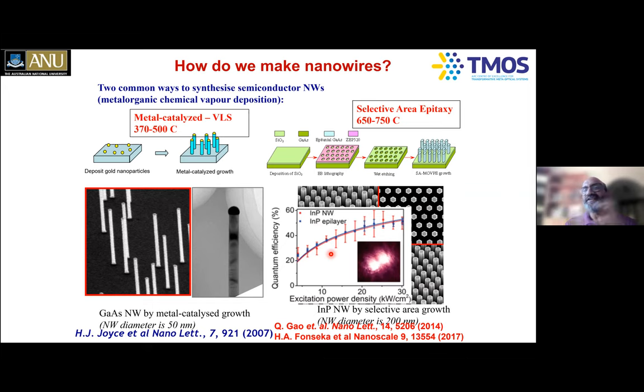And you can make use of these indium phosphide nanowires for making lasers, solar cells or infrared detectors, whatever optoelectronic devices you want to make, which I will come back to. But that is not always the case. In the case of gallium arsenide, the broken bonds on the surface really create defect states within the band gap of the semiconductor. It creates havoc in terms of the light emission properties of gallium arsenide, so we had to passivate the surface in order to create a core shell structure and avoid that particular problem, which again, I will not have time to go into the details of.